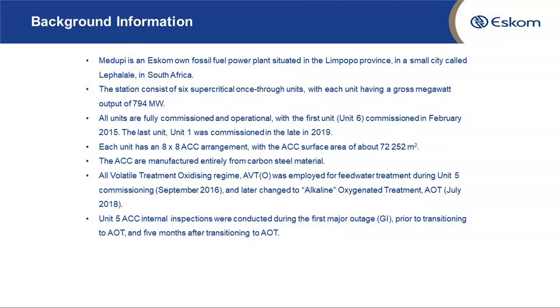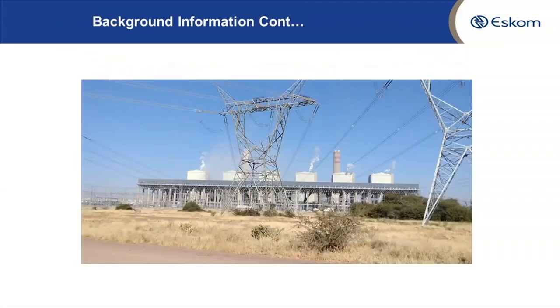For Unit 5, alkaline oxygenated treatment was implemented in July 2018. Unit 5 ACC internal inspections were conducted during the first major outage prior to transitioning to alkaline oxygenated treatment, as well as 5 months after transitioning to alkaline oxygenated treatment. So what we are going to see here is the appearance of internal surfaces when the unit was employing all volatile treatment oxidizing regime, as well as after transitioning to alkaline oxygenated treatment regime, to see the difference or the benefits. Can move to the next slide, Scott.